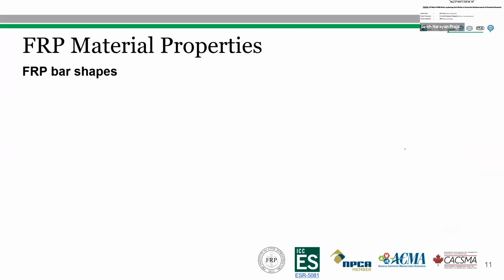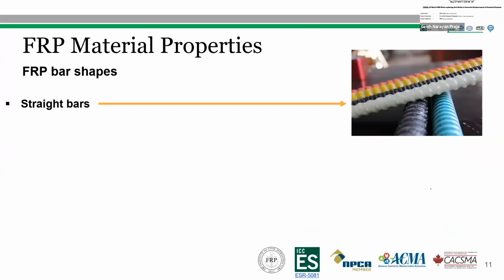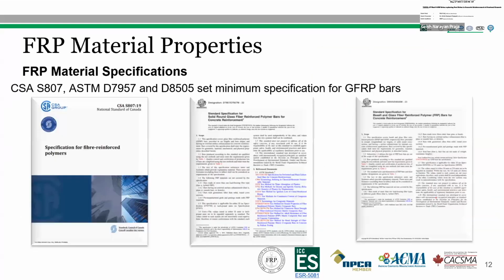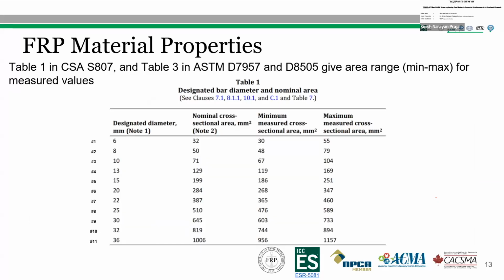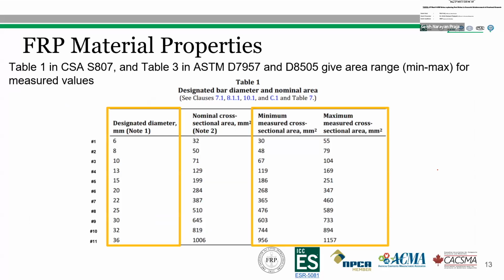The different available FRP bar shapes for reinforced concrete structures are straight bars, bent bars, and spirals. The Canadian and American material specifications such as CSA S807, ASTM D7957, and D8505 set some minimum qualification and quality control properties for the GFRP bars. So we'll go through them. Same as for the steel bars, table 1 in CSA S807, and table 3 in ASTM D7957 and D8505 provide GFRP bar diameter and area ranges for measured values for any GFRP bar external surface.